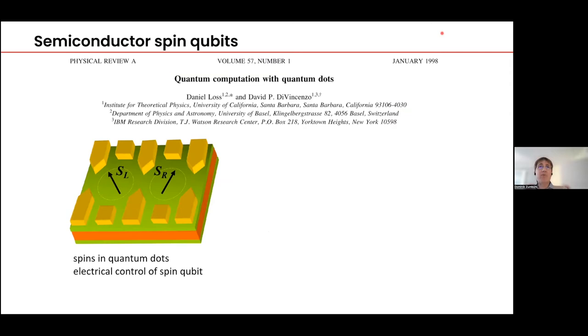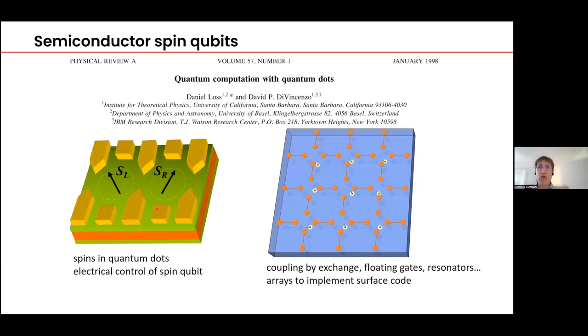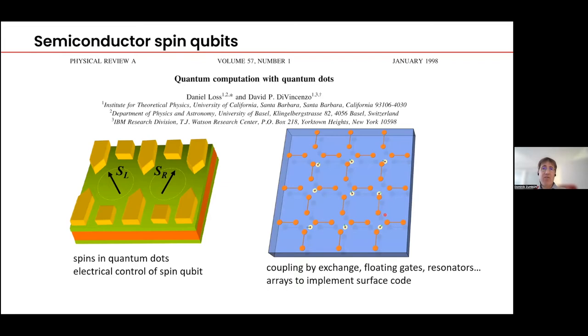On the semiconductor side, there is the well-known proposal by Daniel Loss and David DiVincenzo from 1998 to build qubits using spins in semiconductors. They also proposed more complicated arrays with floating gates connecting individual spins. Based on this idea, people quickly moved away from III-V materials — which were easy to manufacture but gave unstable spins — because of the nuclear spin bath prevalent in those materials. Silicon has low natural abundance of nuclear spins, as does germanium — only five to ten percent — and it can be purified to be nuclear spin-free in principle.